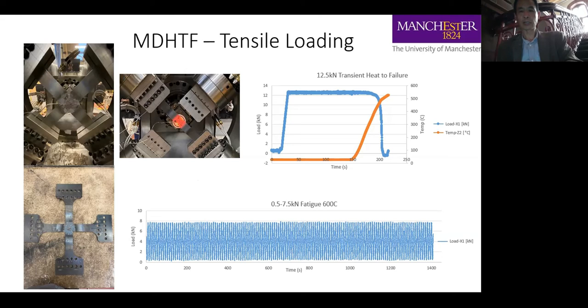This just shows you the load can be maintained. If you can see my cursor, the blue line is the load, which is maintained, and then the orange line is where the temperature is increased. And at the bottom picture, it just shows you we're doing high temperature fatigue testing. So we can then increase the specimen to whatever temperature we want, and then cycle the load to introduce fatigue at high temperatures. So at the moment, the facilities are being built. They are installed in the laboratory and are now being commissioned, so it should hopefully be ready for use in the next few months. So that's me.